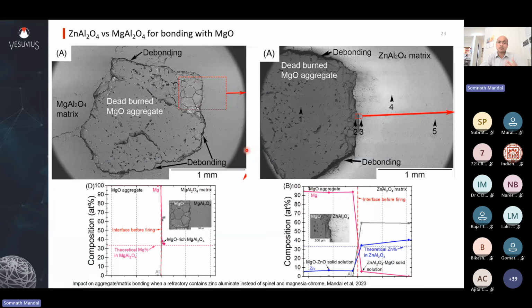Now, one of the challenges with magnesia spinel materials is that it debonds and you don't get very good bonding. If you look at EDS analysis, you see that there is very little interdiffusion from either side. So this prevents you from having good bonding. Whereas if you have a zinc aluminate matrix, you see that a large amount of zinc penetrates deep into the magnesia side, and this gives you a better chance of forming a bonding phase. And this interdiffusion is further enhanced if you have spinel, magnesium aluminate spinel, in the matrix.